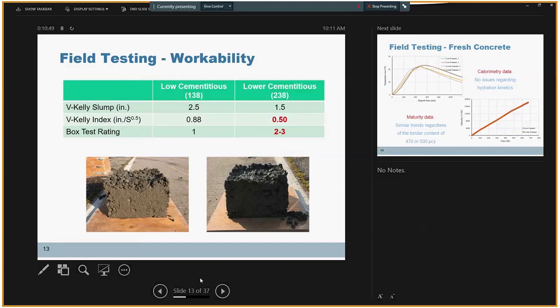But in the case of concrete prepared with lower cementitious materials, i.e. 470 pounds of binder per cubic yard, the workability indexes were not that desirable. We had some problems with workability. The V-Kelly index was lower than the desired rate, at 0.5 inch per square root of second, and the box test rating was also not that good. We had a rating of 2 to 3 for different sides of the test, which corresponded to 30 up to 50% voids on the surface of the test specimen after vibration.